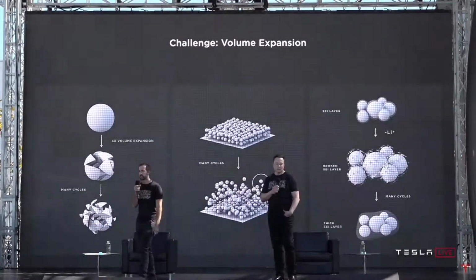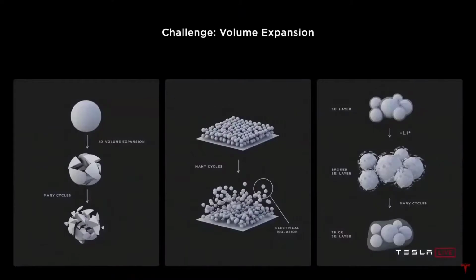The main reason is that the challenge with silicon is that it expands 4x when fully charged with lithium. All of that expansion stress makes the particles start cracking, they start electrically isolating, you lose capacity, the energy retention of the battery starts to fade, and it also gums up with a passivation layer that has to keep reforming as the particles expand.